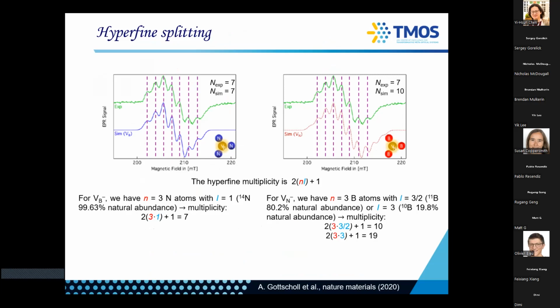And for nitrogen vacancy, you would see many more, which we don't see. So this is the simulation and the measurement, and this is the simulation and the measurement. So you conclusively, straight away, know that you have a boron vacancy defect. This is why in the whole defect community, it's very important to do EPR on an ensemble before you go to singles, because you know what you're working on.